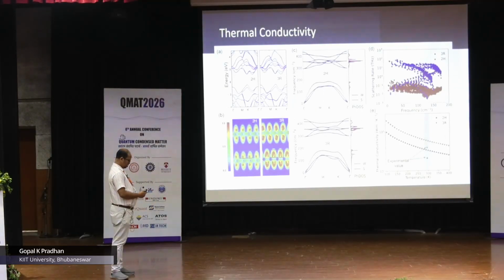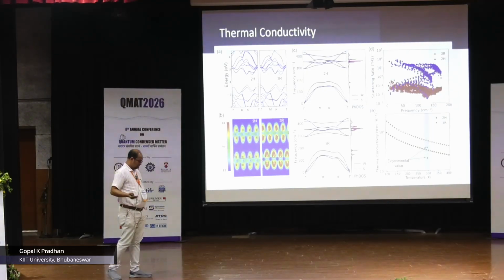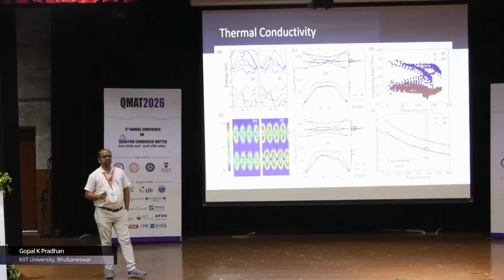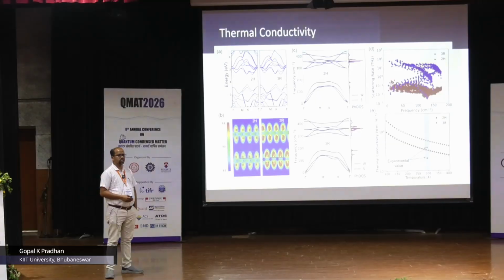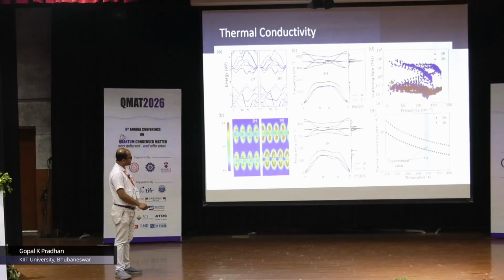Okay, and then of course, a lot of extensive understanding was obtained by calculating the electronic structure and how the electron-phonon coupling happens, and how it affects the rates of different phonons, their lifetimes, and how the 2H phase is different from the 3R phase in terms of phonon spectrum, lifetime, etc. That comes into the picture of modeling the system to understand the different values of thermal conductivity. But you can see here, obviously the 2H phase has lower thermal conductivity compared to the 3R phase.